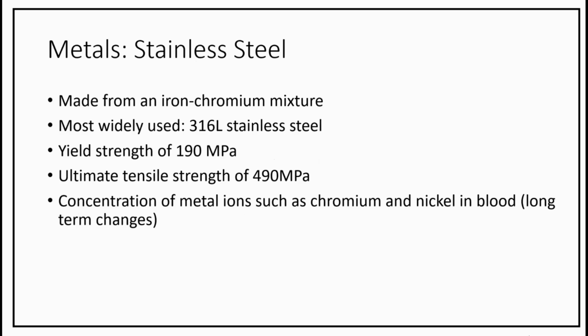Stainless steel is a common metallic alloy made from an iron-chromium mixture. Traditionally, biomedical devices using stainless steel also contain nickel, but nickel-free stainless steel has greatly improved corrosion resistance. One type of low-carbon stainless steel that is widely used in implants is 316L stainless steel. Studies show that 316L stainless steel has a yield strength of 190 MPa and ultimate tensile strength of 490 MPa, making it an ideal candidate for physiological load bearing.